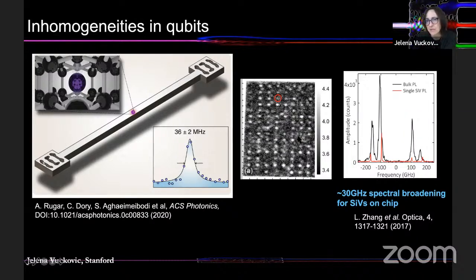And then the spectral inhomogeneities are basically discrepancies between transitions of different atoms, which are a result of the changes in the environment. And again, in solid state, it's not vacuum. It's impossible to really perfectly control environment. We try to make it as close to perfect lattice as possible, but that's never really the case. And then there are discrepancies between different transitions that we have to address. And at best, we've seen 30 gigahertz spectral broadening, for example, for silicon vacancies. And in fact, I think Shallo was a co-author of this paper also when he was in my team, but we're trying to overcome that and reduce it further and overcome this spectral broadening in our experiments.